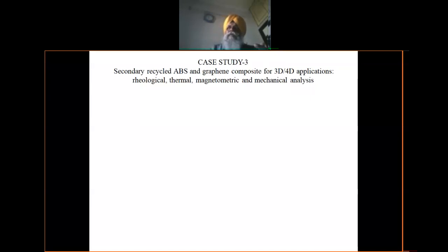into the acetone and everything is in the semi-liquid state, then if I put some dispersion of usually Al2O3, silicon carbide or graphene into it to add some property, the dispersion will be more uniform, right? So that is a chemical way, that is also called the tertiary way of recycling. When primary, secondary and tertiary, these three recycling fail, then we have a quaternary way of recycling. Basically in the quaternary way, what we actually do is we use it as an energy recovery process, basically as a source of energy, right?